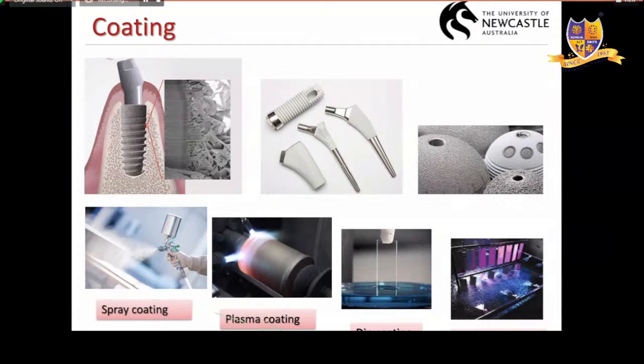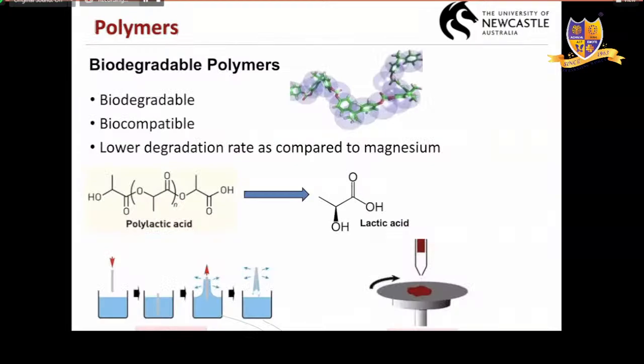But these coatings are not suitable for temporary implants because they are very robust coatings, right? We don't want highly resistant coatings. We need something that'll dissolve over time, right? But it should be better than magnesium. We looked back into the polymers, which I talked about, this PLA, PGA. These polymers are biodegradable. They can't be an implant by themselves, but as a coating, they could serve some purpose, for their biocompatibility and low degradation rate as compared to magnesium.